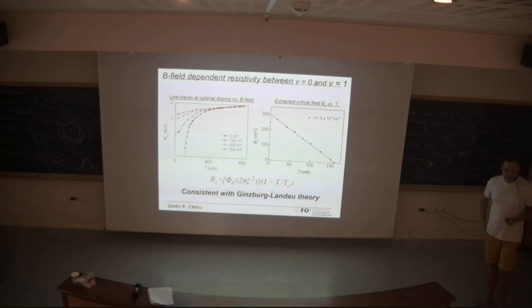Then we can apply a perpendicular magnetic field to try to kill the superconducting state. For all 4 states, we observed that applying a field on the order of 300 millitesla completely lifts the superconducting state, and we recover metallic conduction. And this linearity, which could be the strange metal phase, is fully recovered. This linearity continues down to the lowest temperatures. From these curves, we can extract a critical magnetic field as a function of temperature. We find that it's well fitted with Ginzburg-Landau theory. And from these plots, we have extracted the coherence length.